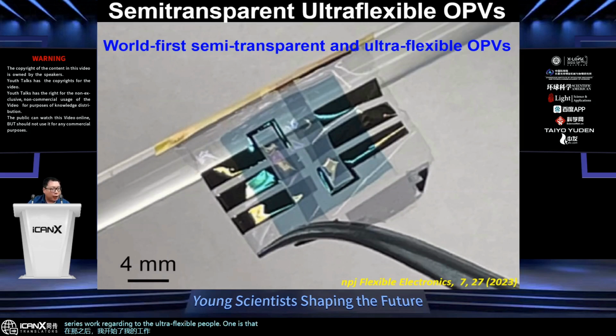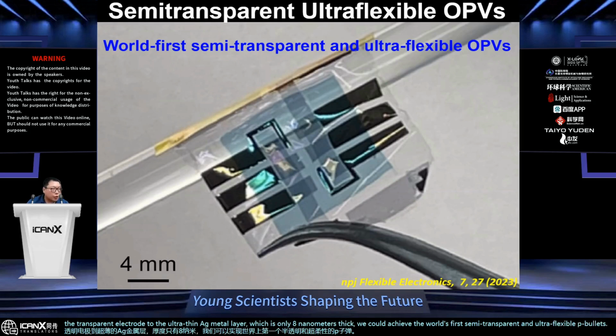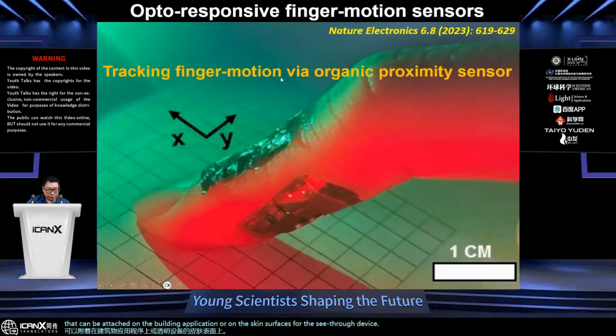And one is that by changing the transparent electrode to an ultra-thin Ag metal layer, which is only 8 nanometers thick, we could achieve the world's first semi-transparent and ultra-flexible cells that can be attached on building applications or on the skin surfaces for see-through devices. And I'd like to briefly introduce my latest work, which is tracking the finger motion via organic proximity sensors. As you can see, when devices are flipped over onto the skin surfaces, we can track the positions of the devices